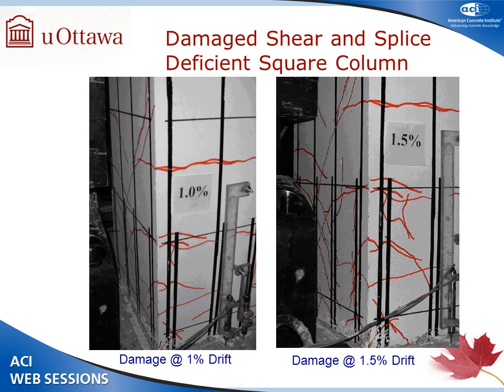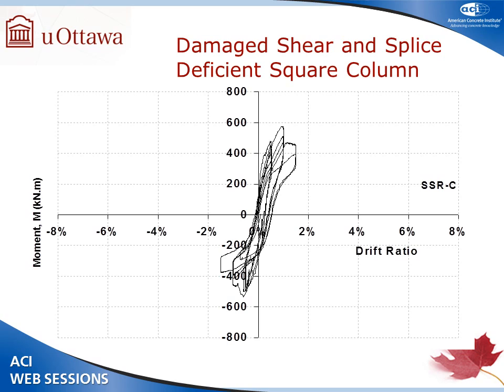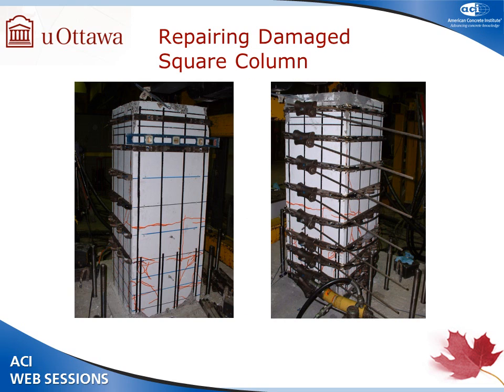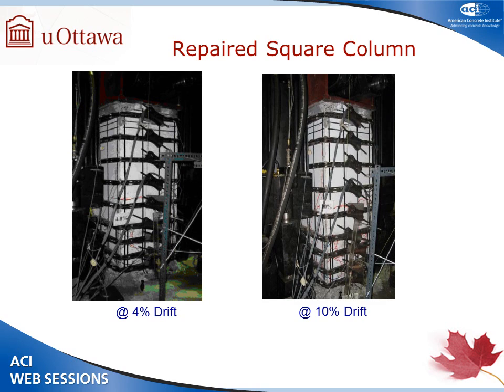And then next specimen involved damaging shear-dominant column having inadequate splicing. And in this case, we looked at square column, and once again, we had this column stopped at about 1.5% drift, and then we applied transverse prestressing. As you can see, we did go up to 4% drift, maybe 3% drift without much problem, but then it started slipping because we had already broken bond. Up to 1% is okay, but the moment you go beyond 1% in damaging the column, the reinforcement starts slipping, and prestressing did help up to only 3% drift, but then, as you can see, it started slipping.